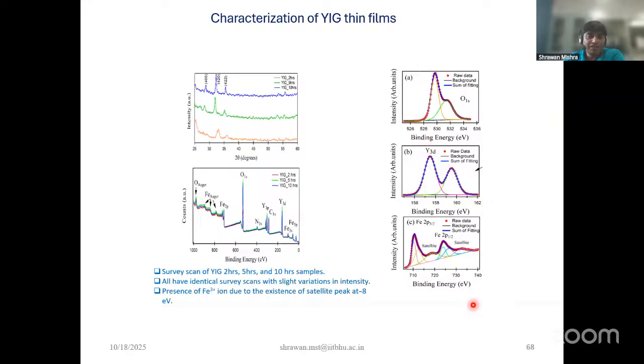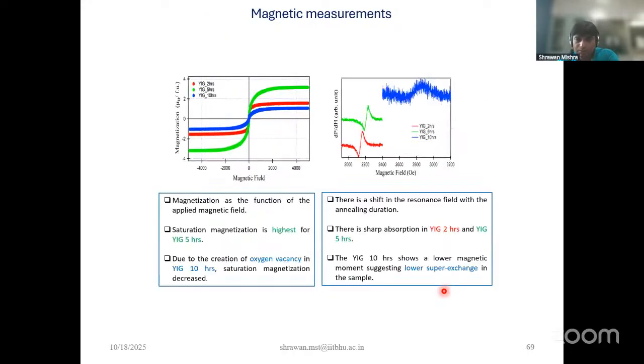And when we are satisfied with this finding, then we move ahead, as the structural and electronic properties of garnet are well established. So now we try to measure its magnetic property, and you can see the hysteresis loops that have been measured to find the conventional magnetization behavior of this material. And this is a measurement done at room temperature. You can see that all the samples that we have grown show well-behaved ferromagnetic characteristics.